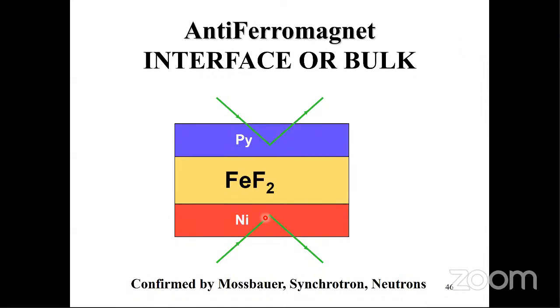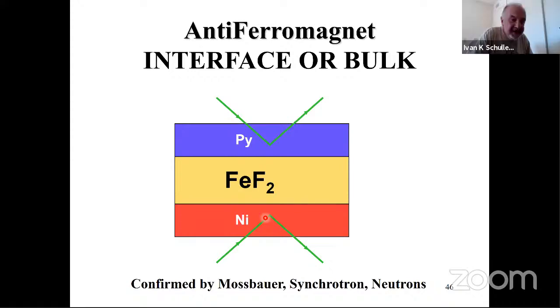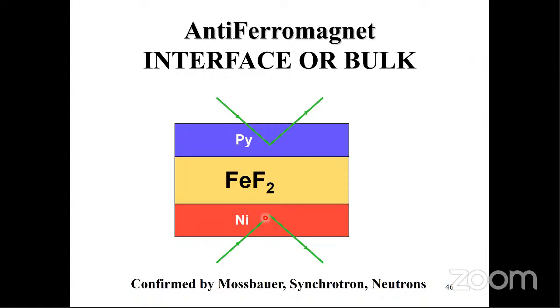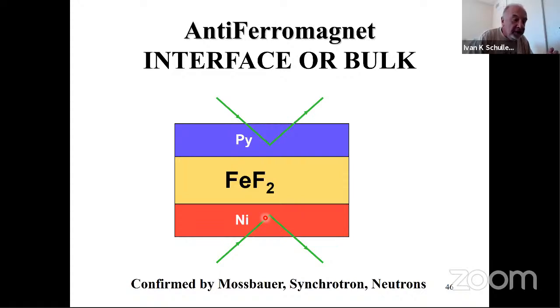Excuse me, we have a question. Is there a dependence on the layer thickness? Yes, there is a dependence on the layer thickness because it's an interfacial effect. And so somehow the interface plays a role. So if the ferromagnetic material becomes very thick, then the whole effect goes away. So this exchange bias phenomenon is only for very thin layers. It also depends on the thickness of the antiferromagnet. And that one is a tricky question to answer, because it may be that if you make the layers very thin, either the disorder in the antiferromagnet becomes very big, or the antiferromagnetic property gets lost in very thin layers. And that's not yet clarified, actually.